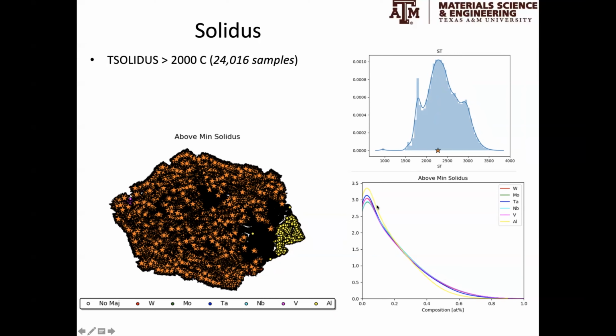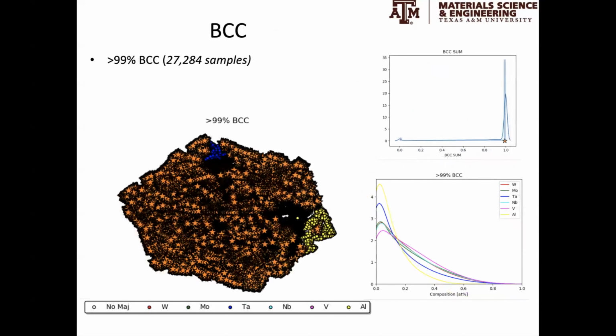Close to this aluminum corner, we can expect the solidus to be much lower because we have more aluminum. Here we see the composition histogram that is not as heterogeneous as in the previous case, but we see that aluminum alloys tend to be less represented than the rest of the chemistries, because the more aluminum you have, the more likely it is that you're going to have low solidus temperature.